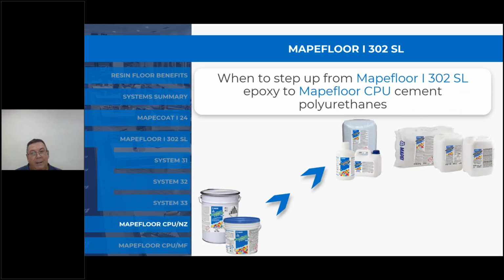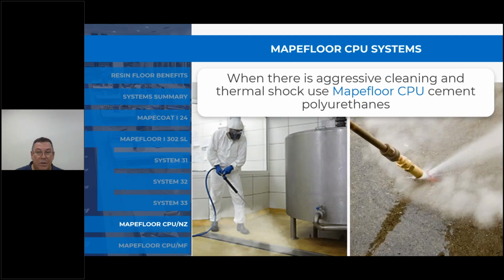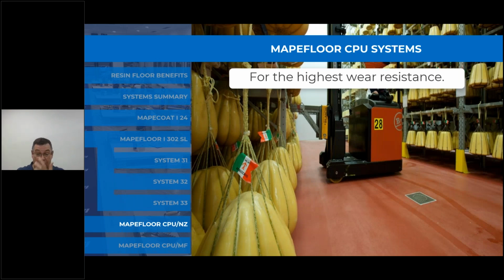So when would we step up from an epoxy resin floor to a cement polyurethane system? A choice that can be made once you understand the attributes of the different products. When there's aggressive cleaning, any thermal shock issues where steam cleaning is required or it goes from cold to hot very quickly, the Mapefloor CPU cement polyurethane systems are certainly the answer. They will withstand thermal shock considerably better than an epoxy resin system. They have the highest wear resistance, so where forklift traffic and lots of robust abrasive requirements are needed, then the CPU system is certainly beneficial.